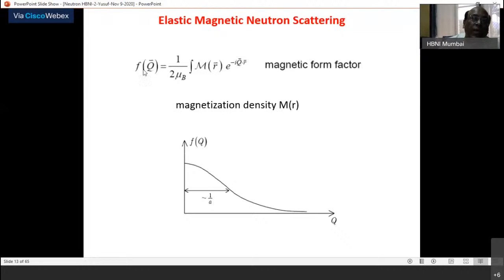So you get form factor. Now here, form factor is relevant for magnetic scattering because your probe de Broglie wavelength is again angstrom, because it is a neutron of milli-electron volt energy, and the magnetization density distribution, that structure, is also of that length scale. As you know, the atomic shell, that orbital dimension, is also about angstrom.